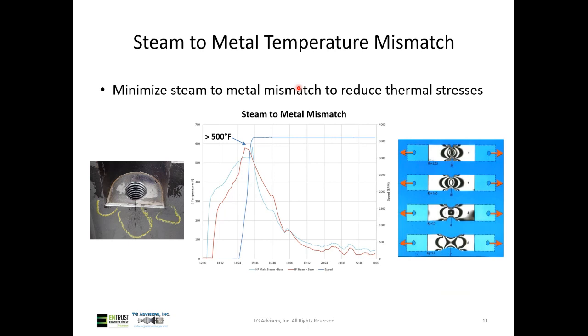Or another way to look at it is, if you've ever taken a glass pan out of the oven that's hot and you were to put cold water on it, it would just shatter, right? So we want to keep the steam to metal mismatch low because we want to keep the thermal stresses low. But at the same time, if we don't have any mismatch, then we don't get any heating. So the higher the mismatch, the quicker it'll heat, but the more stress. So we've got to manage these things.